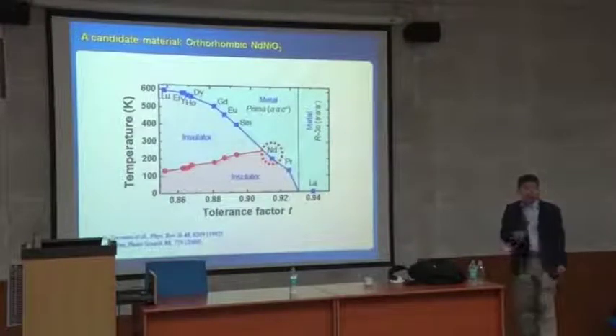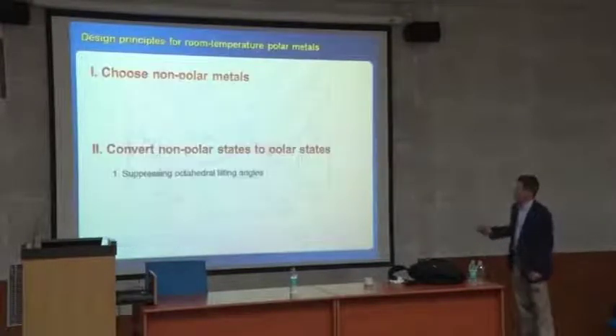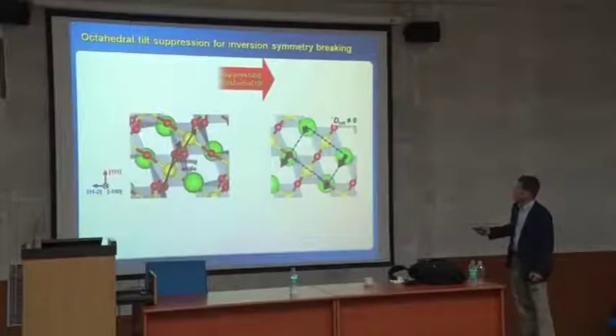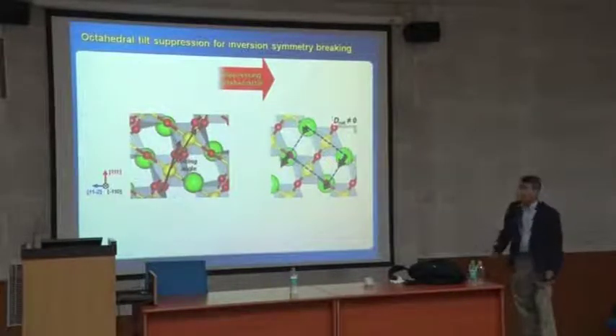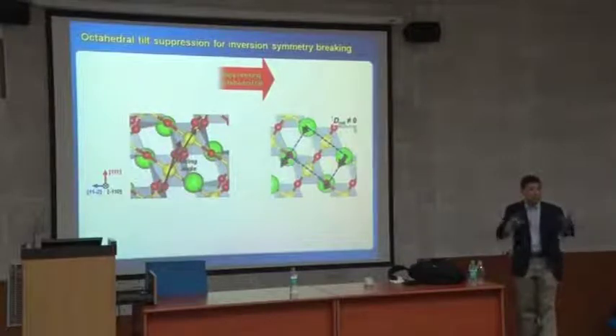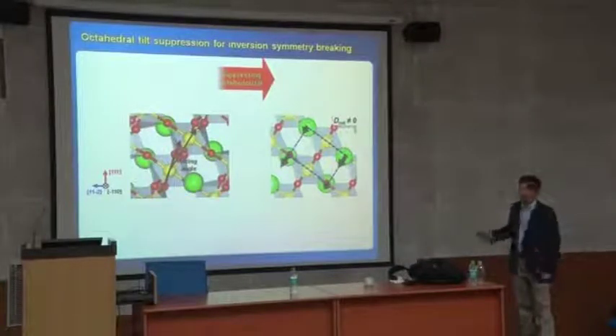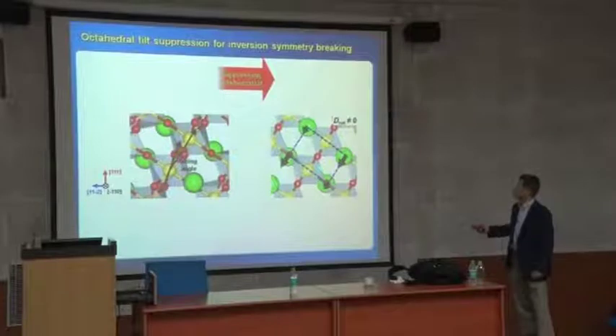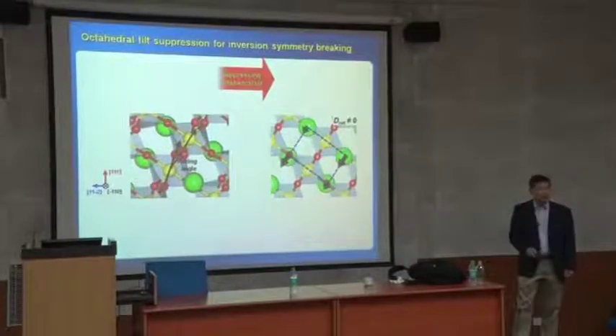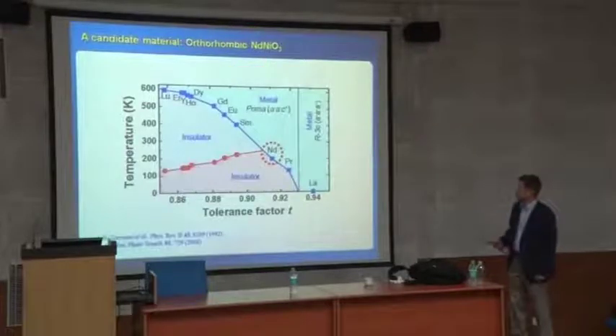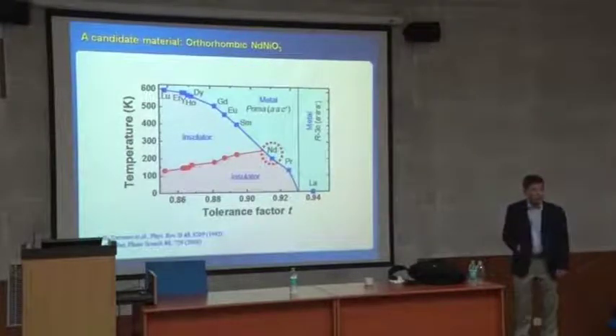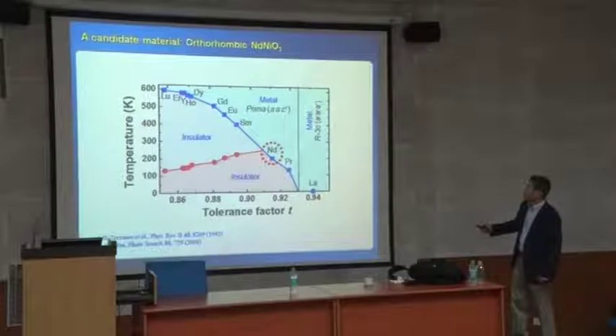And then the system, you have this kind of concept of this is antipolar, but you start with already its actual tilting angle is a non-zero state, like a large tilting angle, and then you can drive it to stretch it that way, then you can make a polar system. So which system has this one? You have this